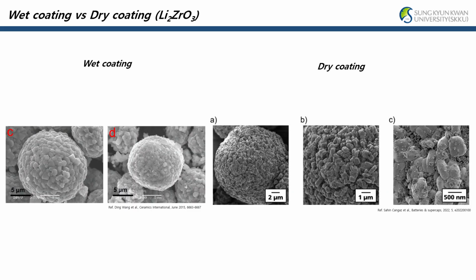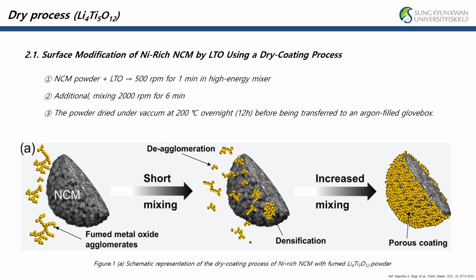The figure below is observed with SEM after coating with a wet chemical method and dry process. It can be seen that the surface of wet chemical is smooth when viewed at a low magnification, but the surface of dry coating is not smooth, as if it is not uniformly coated. The cathode active material by the dry process has a relatively simple experimental process.